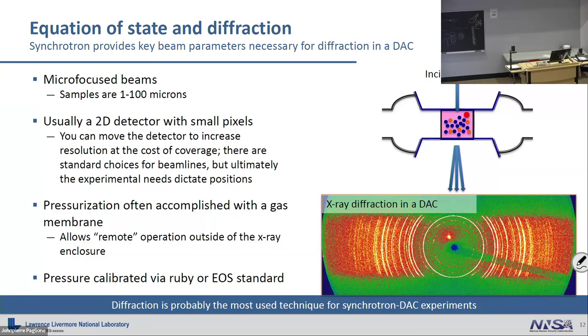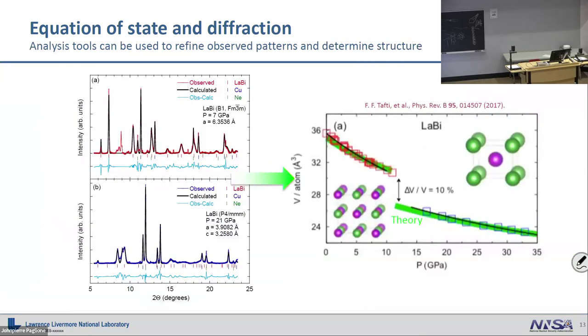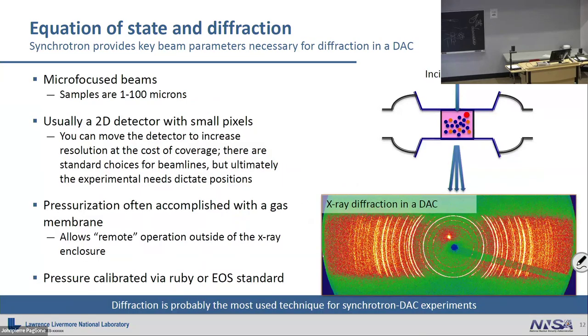And that's a big challenge in the community as well, as we go to these multi-crystal type diffraction setups. Oh, there's one other thing I wanted to mention, this very bottom one. So oftentimes we talked about ruby. That's a great pressure calibrant, especially if you're not doing diffraction. If you're doing diffraction, Adam kind of mentioned this a little bit, in this I'm saying blue is sample and orange is my EOS standard. So let's say it's copper, something I know doesn't have a phase transition, I know is not chemically active. I very much like to have that in the pattern.